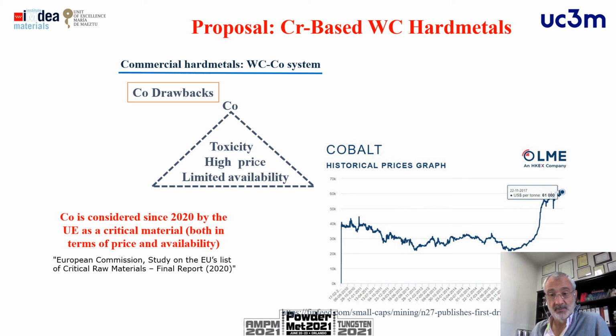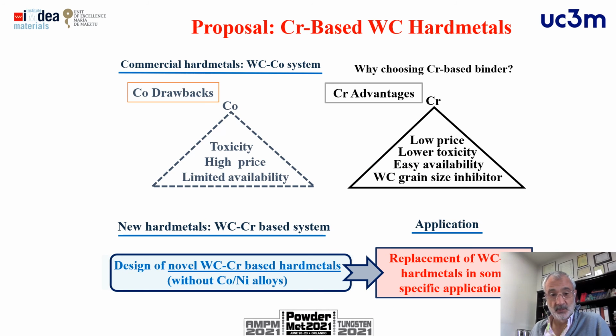So it could be interesting to replace cobalt, but the problem is that cobalt is the best binder for the cemented carbides due to the good combination of cobalt with the tungsten carbide during the sintering. So in our case, we want to design a novel tungsten carbide chromium-based hard metal without cobalt or nickel, that also has some problems of toxicity and price. The idea is to replace the conventional tungsten carbide cobalt hard metals in some specific applications, not of course in all the applications.